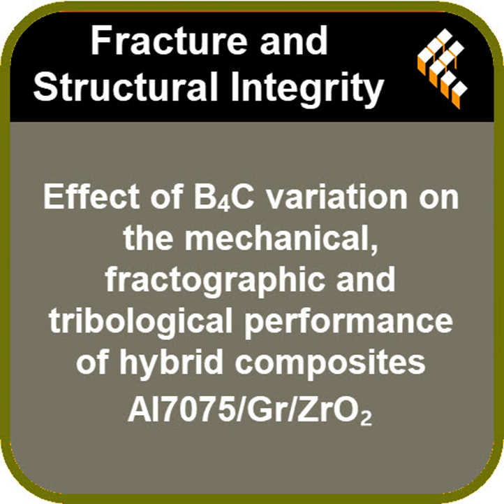4%. Okay, so let's start at the foundation. The microstructural integrity. The SEM imaging confirmed these particles weren't just floating around in there. No, not at all. You get a really uniform dispersion. The GR, the ZrO2, and the B4C were all strongly bonded within the aluminum matrix, and that's essential. You have to have that foundation.